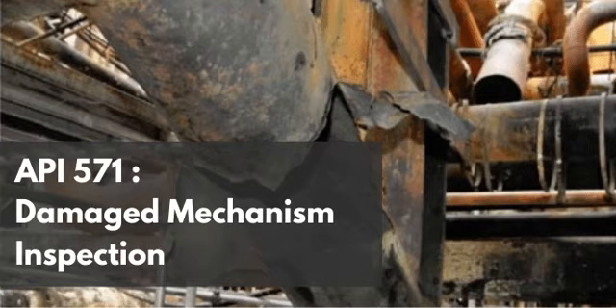That's exactly what happens. If carbon steel and low-alloy steels are this vulnerable to cold work and welding in these environments, the immediate engineering response is to look at alloy upgrades, right? Always. And the documented upgrade paths include solid or clad 300 series stainless steel, alloy 400, or other corrosion-resistant alloys. Yeah, and by upgrading to a 300 series austenitic stainless steel, we are fundamentally changing the surface chemistry. We are no longer relying on a fragile iron sulfide or iron carbonate film.